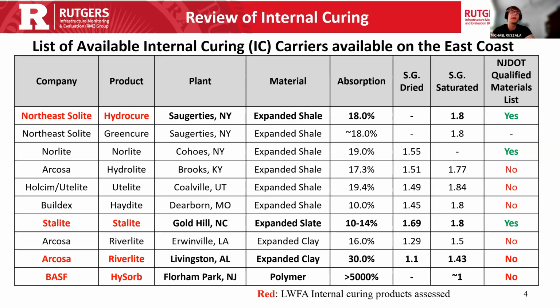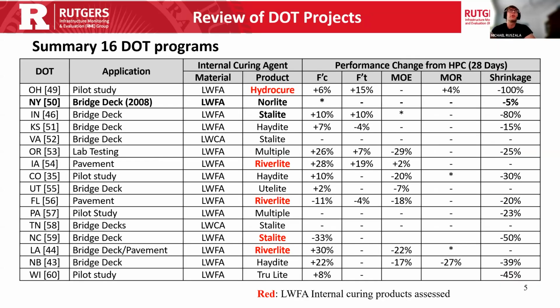And there's a more experimental product, HySorb. It's a super absorbent polymer. So it's effectively like a water bead that you would put into the mix, and it releases the water stored in it, but it leaves a void, while these lightweight fine aggregates are effectively a stone. So that's a little bit of a difference. These super absorbent polymers aren't very commonly used, but it is an interesting technology, and it's very straightforward to implement.